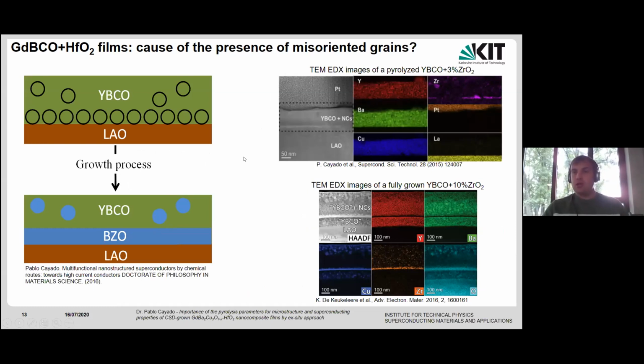This can be correlated very well with something that we discovered years ago in these two papers. That is that in certain conditions, the nanoparticles that are already preformed tend to agglomerate or sink and go to the interface. Then, during the growth, this layer of continuous particles reacts and forms a continuous layer of BZO in that case, and in this case BHO, because these nanoparticles, which are hafnium oxide, react with the barium and form a continuous layer.